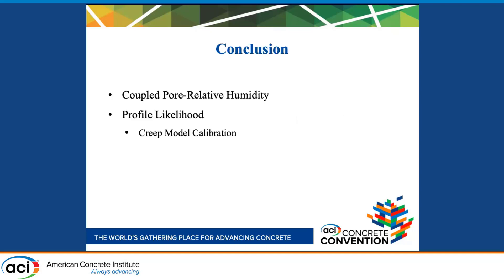In conclusion, we found that a coupled pore relative humidity model can capture both mechanisms of shrinkage using a single total shrinkage coefficient. The profile likelihood method helped us incorporate the large amount of data needed to calibrate our shrinkage model. We plan to repeat the same process for creep, which should be easier now that we know how to calibrate a time-dependent model.